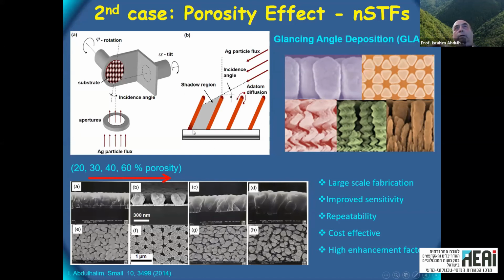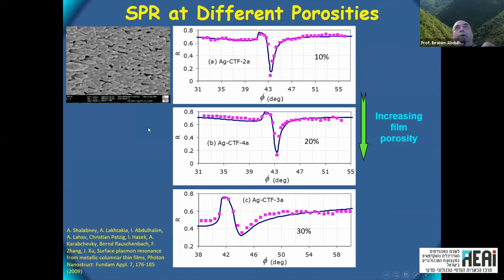So you can get surface plasmon, extended plasmons from this structure, but you might also get a localized one on the tip of the nano columns. So you can win in both directions. First, we went into the extended plasmon to prove this claim. And we were surprised, actually, to see very nice resonance at 10, 20, up till almost 30%. And the sensitivity does increase as you increase the porosity.